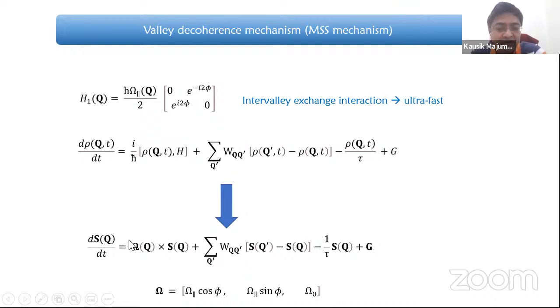This has an omega cross S term, which basically comes from the precession around this kind of pseudo-magnetic field. There is also a scattering term. Please note that if you only have the scattering term, it does not degrade any polarization, because it is diagonal. And then, of course, there's a lifetime term, and this is the generation matrix.